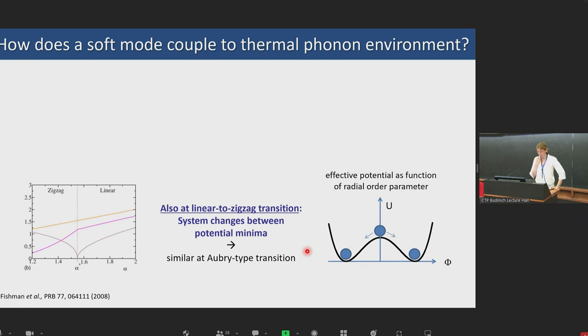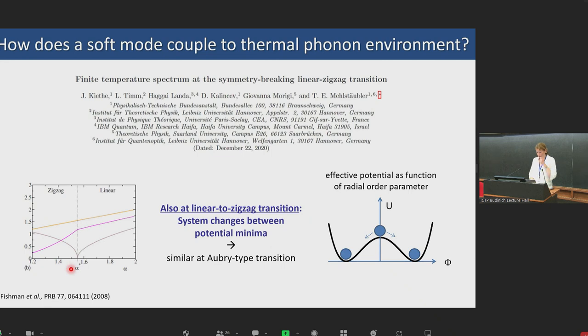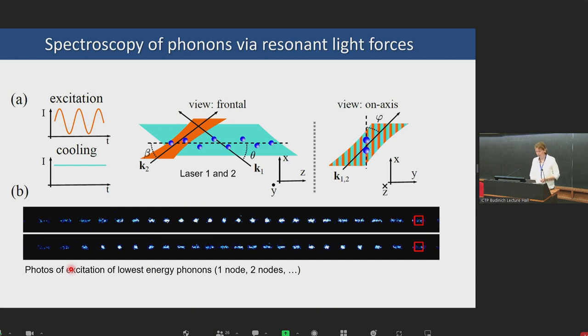This is the summary of the nanofriction. We had seen the first onset of symmetry breaking, non-analytical hull function for the first time, and also the soft mode. We also realized you would have to go to a microkelvin to really see this soft mode vanishing or to even go quantum one day. Nevertheless, we have seen that the breaking of the commensurability by a topological defect was reducing the friction, also static friction, by more than an order of magnitude in our system, really making the system slide much easier. We were very delighted to find that this is actually really similar to what in biophysics was observed in simulations of DNA unfolding. When you have a kink, a mismatch in the human DNA, then it also can slide and break earlier. It's the same Frenkel-Kontorova dynamics.